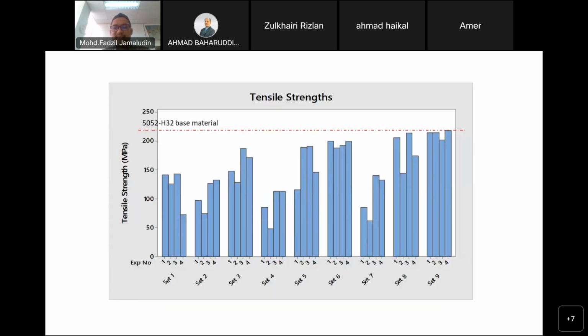In terms of tensile strength, overall, in general, for all samples, it was less than the base material. The tensile strength is less than the base material, but for some of the samples, it is approaching the tensile strength of the base material. As you can see, for set 9, different thicknesses and different alloys, it is approaching the base material strength.